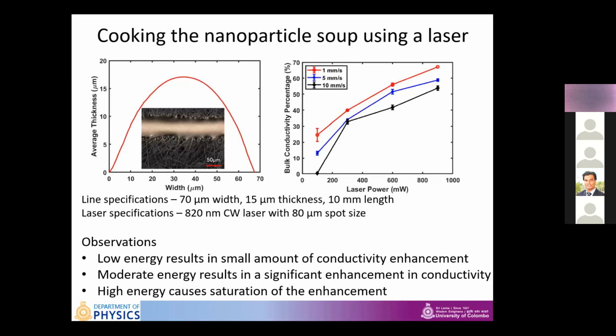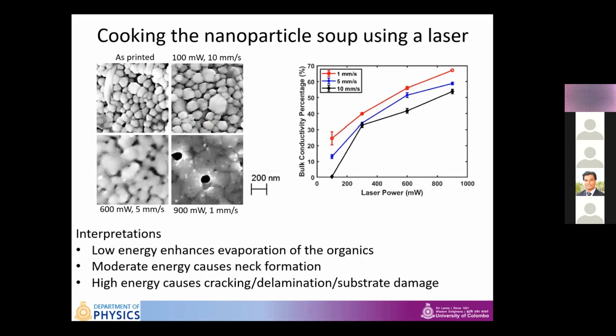Furthermore, at the higher energy end, you can see an increase in trend, but that trend is saturating. And there's a reason, let's see why. So we need to observe this conductive trace under a high magnifying microscope, in this case an SEM, scanning electron microscope, to see what's going on inside the trace that contributes to this change in conductivity.